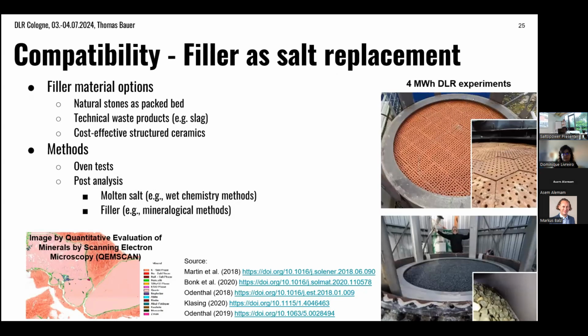Then we also heard from Christian that we can have molten salt in contact with filler materials. So the potential filler materials of interest for nitrate salts are natural stone. We work with, for example, volcanic rock, basalt. Also of interest are technical waste products like slag, for example, from steel manufacturing. The difficulty here is a bit that in the slag you find a lot of elements inside. And as I said, the salt will react with quite a lot of things. So the question is always, is the compatibility really ensured and so on.